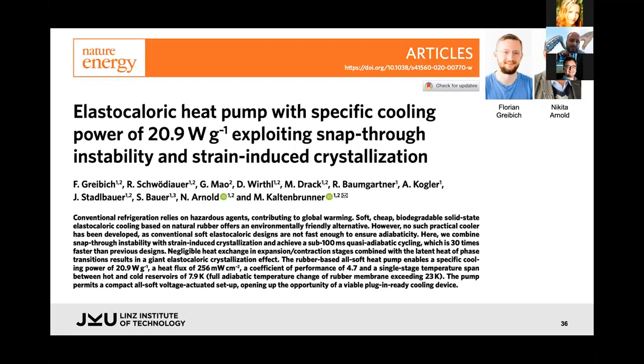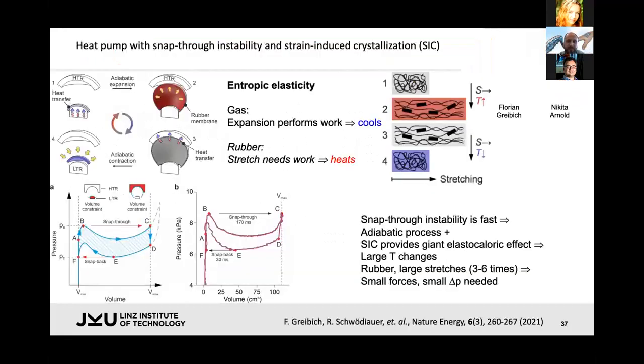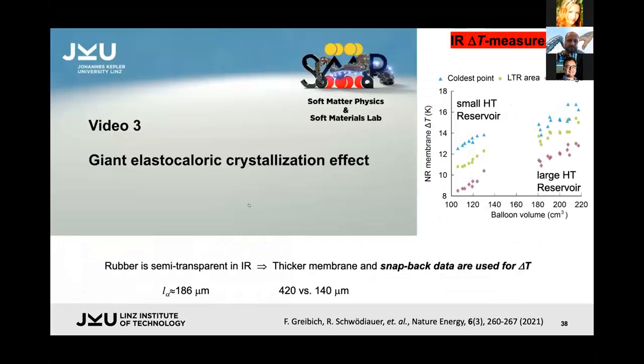And this was the first time that we showed that you can actually make a refrigerator based on nothing else but a rubber band. And the secret is that you need to combine this snap-through instability together with the rubber material that undergoes stress-induced crystallization, because then you have not only the entropy change through the orientation of the polymer chains, but you have also the intrinsic crystallization, which is a first-order phase transition. And if you combine these two, then you can get a device that actually cools quite a lot.